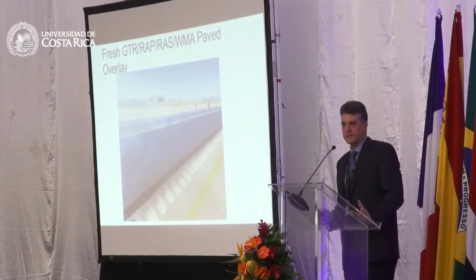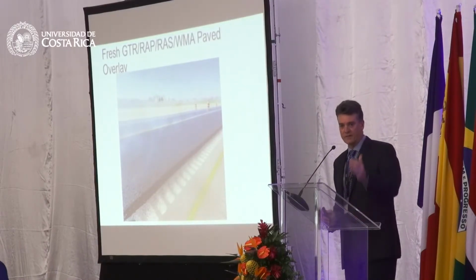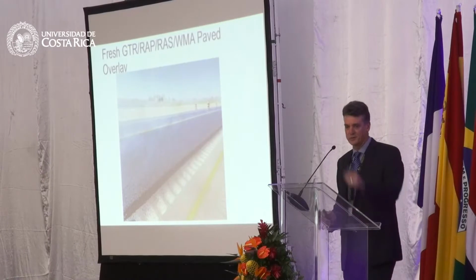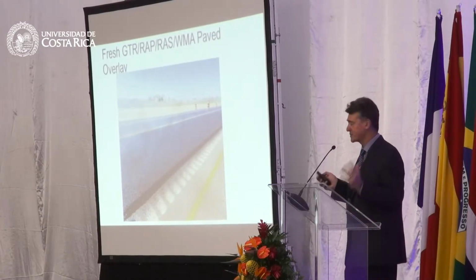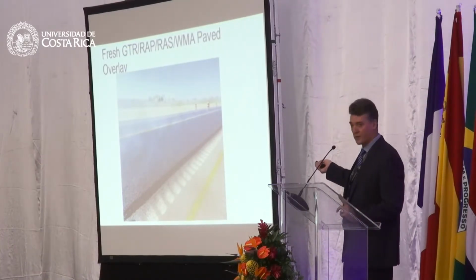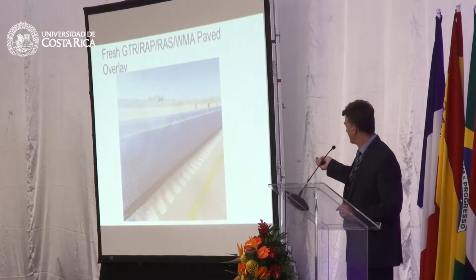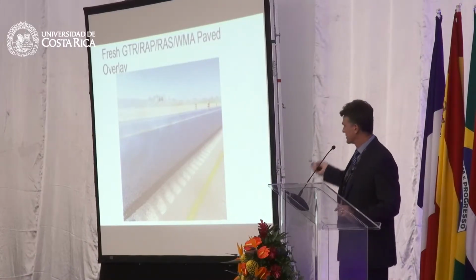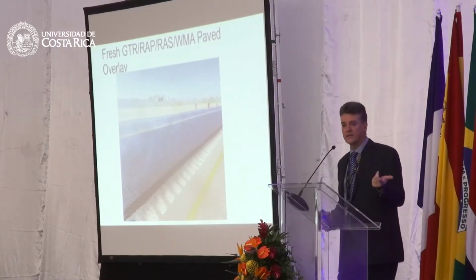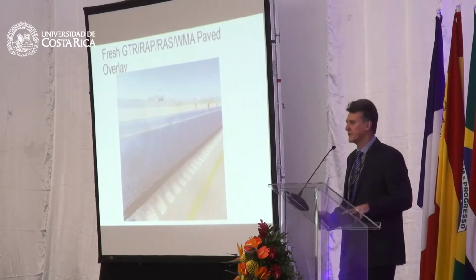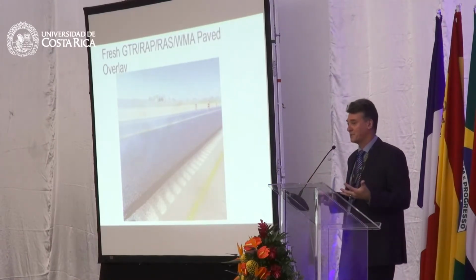And this mix, somebody was talking before about having 5 or 6 modifiers in a mix. I think it was Louise. And actually on the mixture side, we had ground tire rubber, recycled asphalt pavement, recycled asphalt shingles, and warm mix asphalt, not to mention the other modifiers that were in the binders. So there was quite a few things going into these mixtures.